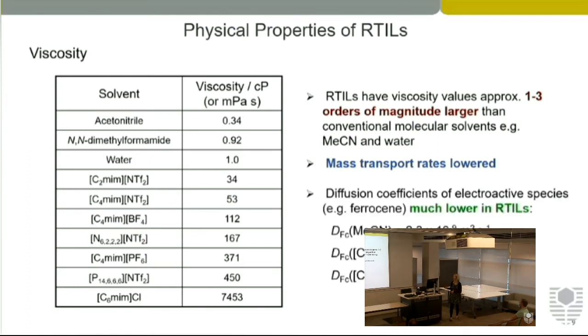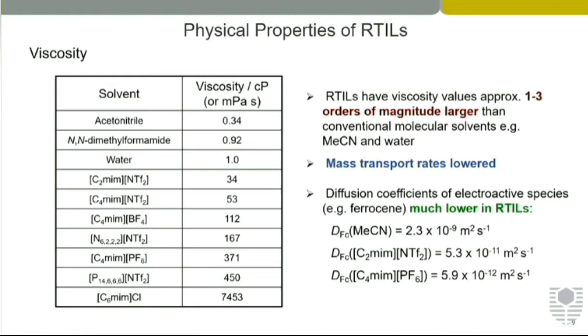And in electrochemistry, that's important because mass transport rates are lowered. What that means is when a species is diffusing through our ionic liquid to get to the electrode, that diffusion speed is much slower in a more viscous solvent. So if you take ferrocene, the diffusion coefficient of ferrocene in acetonitrile is about 10 to the minus 9 meters squared per second, and then that reduces by 2 to 3 orders of magnitude in these more viscous ionic liquids.